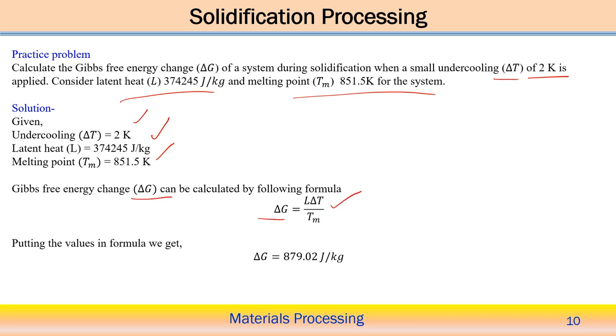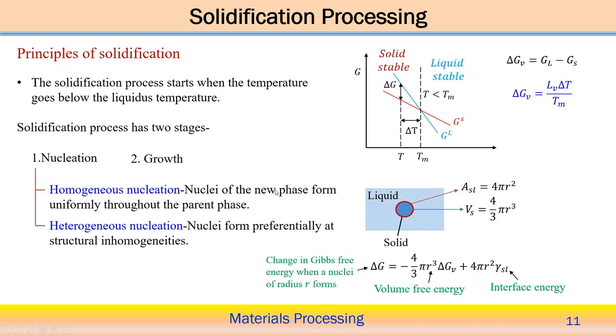We get delta G equal to 879.02 joule per kg. So this amount of driving force is available for nucleation to occur for this thermodynamic system. It is a simple calculation, and we can calculate the Gibbs free energy available for the solidification. Now we can further look into the principle of solidification.